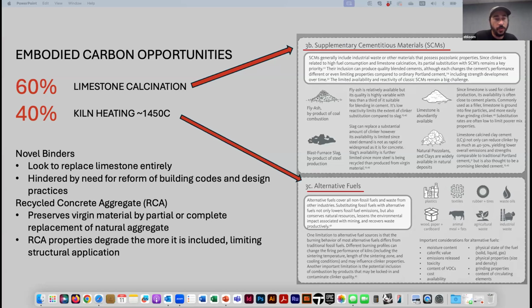And then kind of similar for recycled concrete aggregate, which looks to preserve virgin or natural aggregate with the use of demolished concrete. The main limitations are in terms of performance concerns and the variability of quality, although a number of studies have found that this sort of sweet spot to replace natural aggregate is around 30–35% before you start to see a decline in structural performance. Next slide.